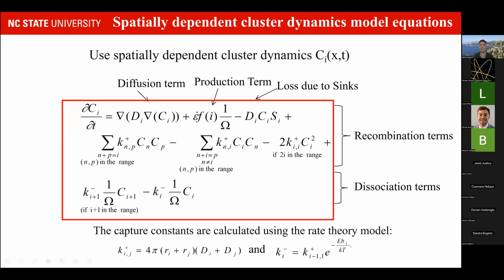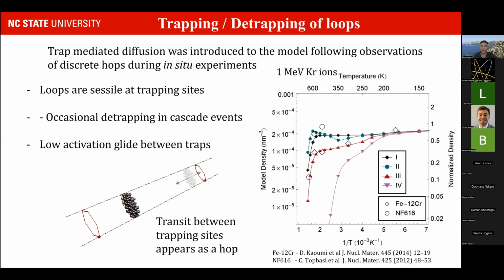All this information is relevant to benchmark models that are based on rate theory. For that specific study, we were working with Brian Worth and his postdoc Aaron Connard, who's now at Los Alamos, and they developed this spatially dependent cluster dynamics to represent what the in situ TEM experiments were showing. And as an example of how in situ TEM can help the modeler, I want to specifically emphasize this ultimate result, where we were giving them the kinetics information we had.